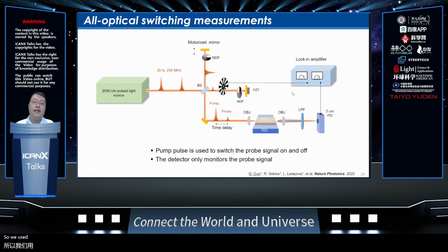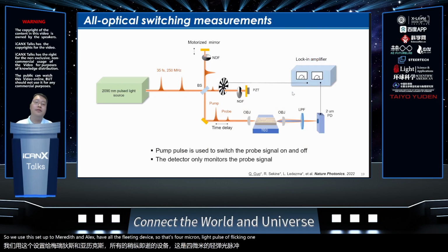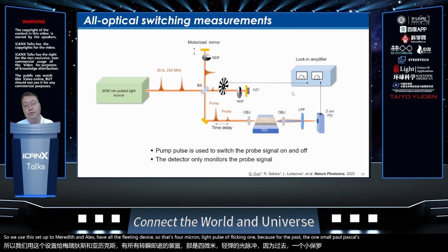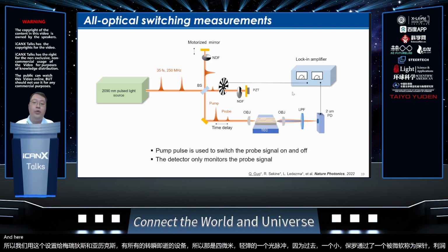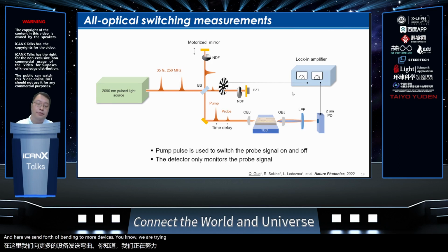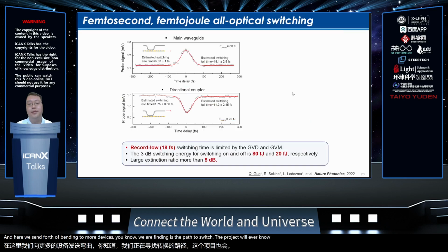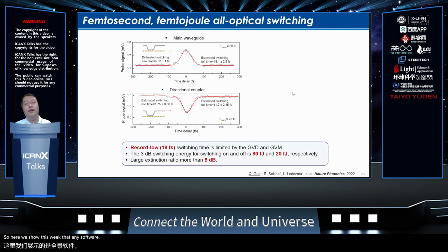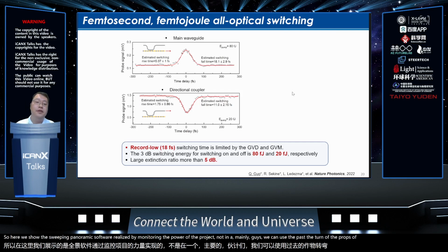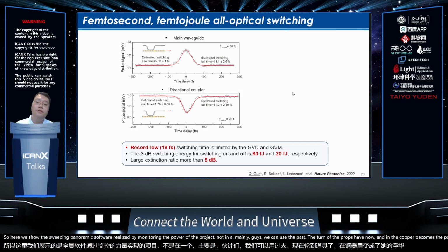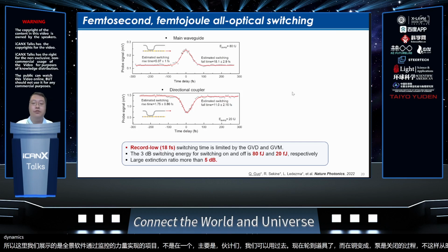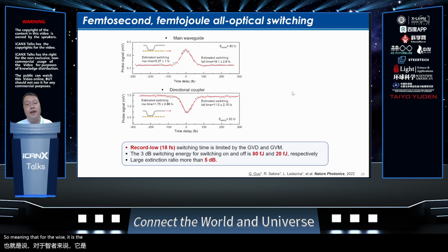So we use this setup to measure the dynamics of our switching device. So the 2 micron light pulse is split into one big pulse called the pump and one small pulse called a probe by the Michelson interferometer. And here we send both of them into our devices, and we are trying to use the pump to switch the probe signal on and off. So here we show the switching dynamics of our device by monitoring the power of the probe signal. In the main waveguide, we can use the pump to turn on the probe signal, and in the coupler, we can use the pump to turn off the probe signal. So from the temporal dynamics, we extrapolate that the switching time is only 18 femtoseconds, meaning that our device is fast enough to even respond to pulses as short as 18 femtoseconds.